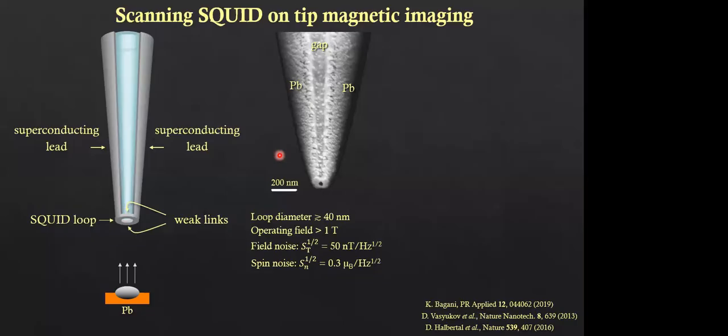There is a question from Joydeep whether the metal deposition is via sputtering or not. It seems very delicate. No, this one is done by thermal evaporation, regular thermal evaporation, but not actually regular, because this superconducting thin film which we deposit on the glass doesn't stick to glass.